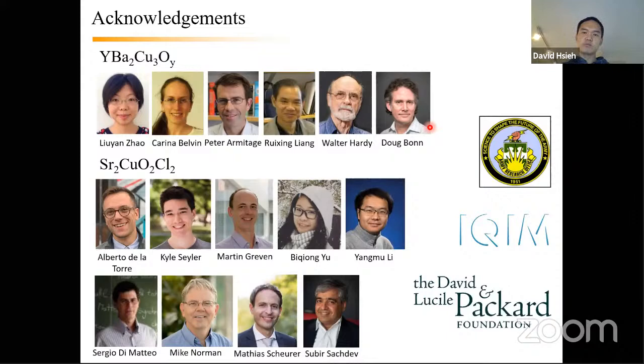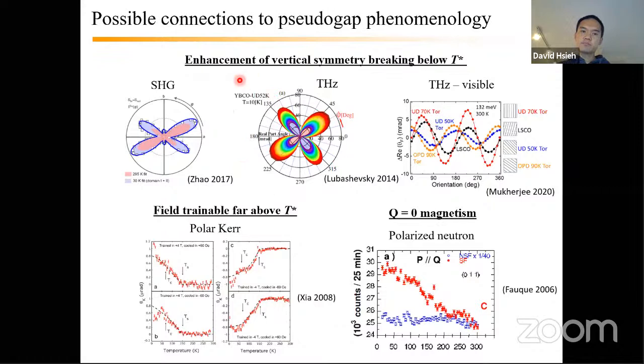Yeah, I think it definitely would. Potentially repeating some of this terahertz polarimetry, both linear, this is linear terahertz polarimetry measurements, on these SCOC compounds would be very valuable. It's a little bit tough because terahertz studies require big samples. Right. I believe these are done in thin films, whereas as far as I know, the SCOC is just in bulk single crystal form. Right. But we can potentially do that in our group on few millimeter sized crystals. Yeah, I think terahertz SHG would be wonderful. It's technically very challenging, but it's something that I think would definitely reveal a lot of information. I just don't know how to do it at this point.